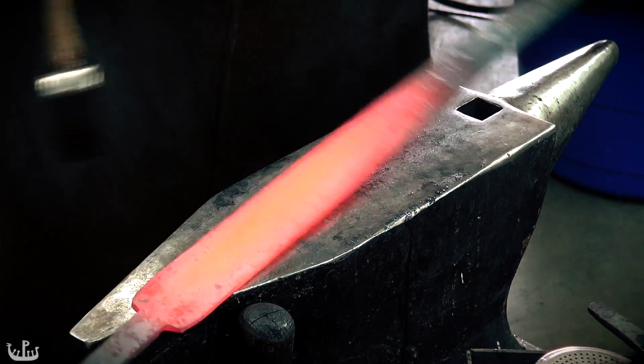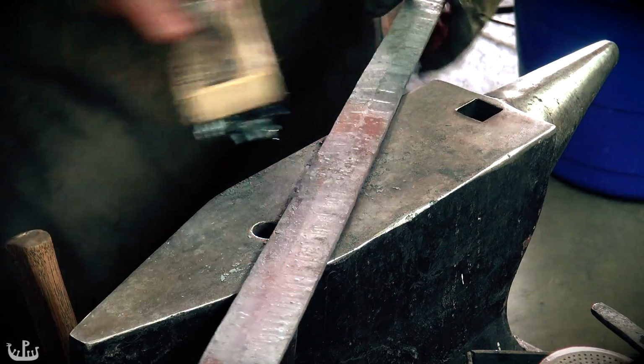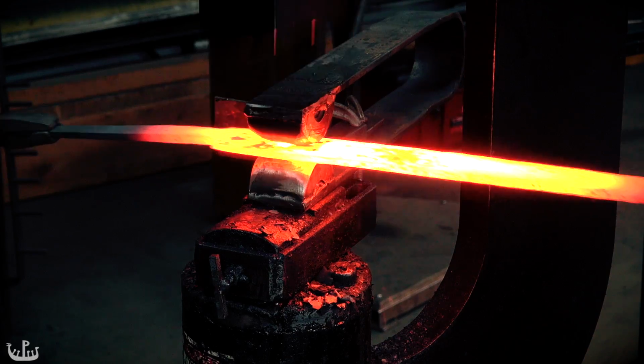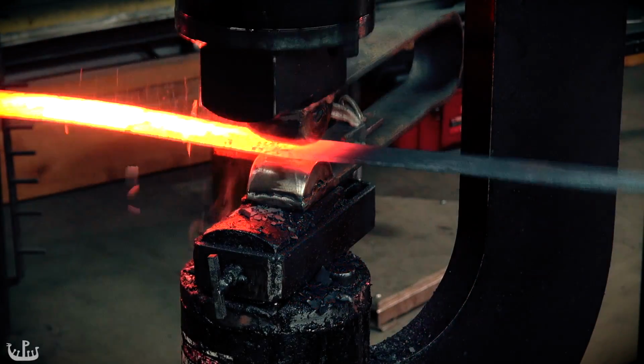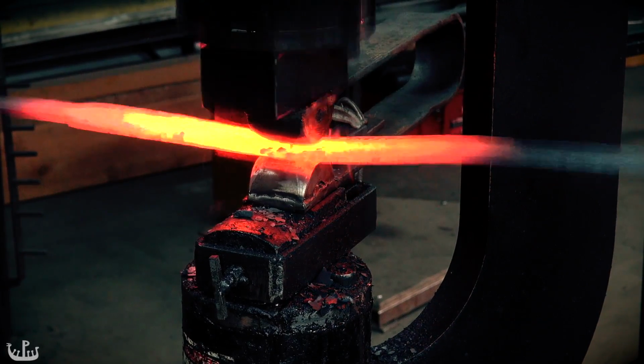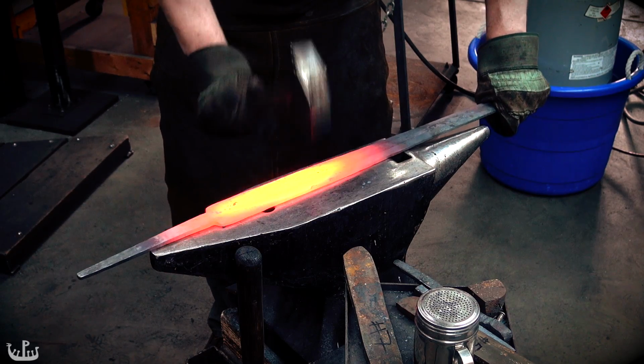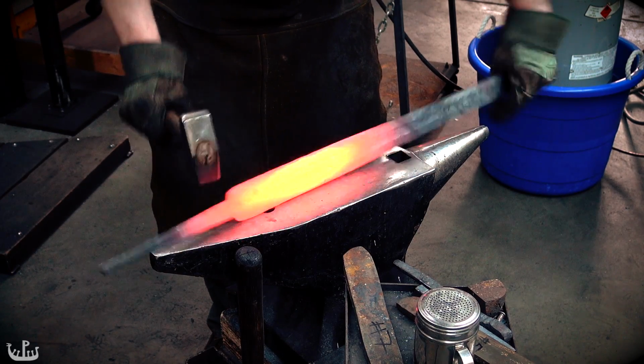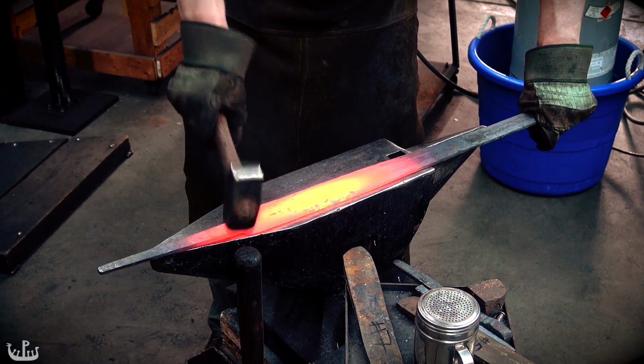While examining the sword after I put in the bevels, I realized that the blade is not quite wide enough. To correct for this, I'm also forging in the fuller. Originally, I had just planned to grind it into the blade. Unfortunately, forging in the fuller after the bevels results in some twisting of the blade, which again I have to correct by hand.